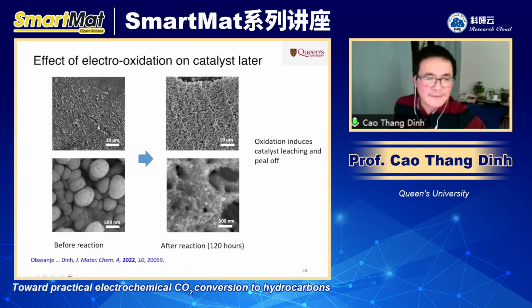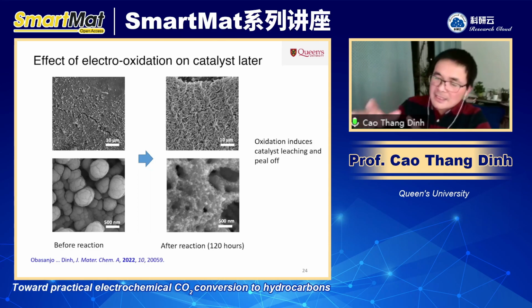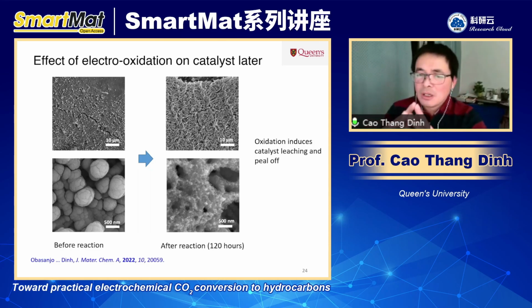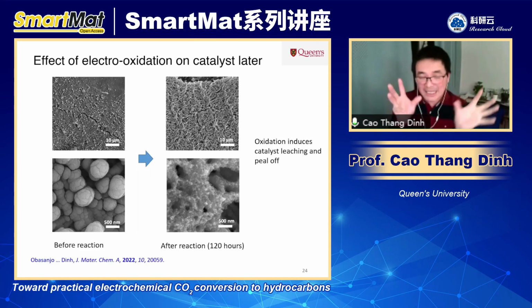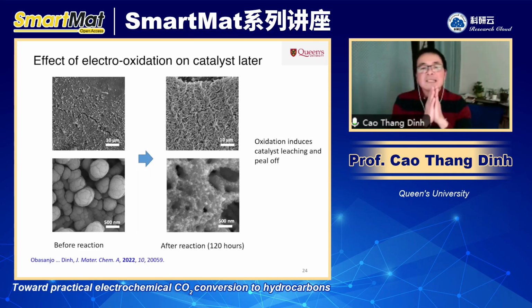So on the left-hand side is the morphology of the catalyst before the reaction. And then we analyze it after like 100 or 120 hours. And we observe that a significant amount of the copper leaves the surface, right? So when you oxidize the surface, you change the local structure at the atomic scale of the copper, but you also change it in the macro scale.